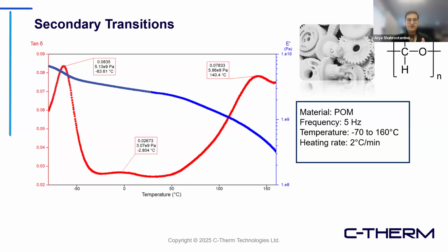So starting at minus 63, around that temperature point, you see the first transition happens, -2 the second one, and the third one 140 degrees C. So this test was done with the frequency of 5 hertz and the temperature of -70 to 160 degrees C and heating rate of 2 degrees C per minute.